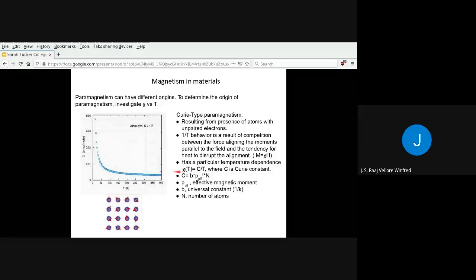So what we can infer from this graph is the effective magnetic moment of your sample, from the equation shown over here. This 1/T behavior is given by this equation, where C is the Curie constant. Once we get this information from the SQUID magnetometer, we can find out the value of C for the particular material. And then, by knowing the universal constant, which is 1/the Boltzmann constant, and the number of atoms in the sample, we can measure the effective magnetic moment.